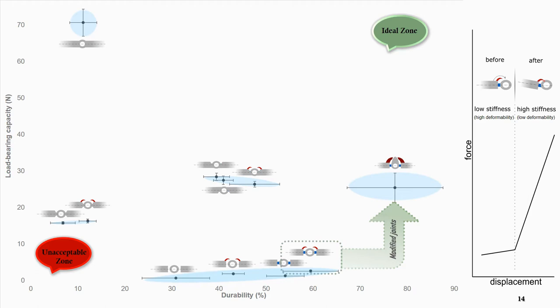First, a high deformability regime prior to the spikes activation in which the deformability of the joint is determined by the stiffness of its material. Second, a low deformability regime after the spikes activation in which the stiffness of the joint is increased due to the interlocking.